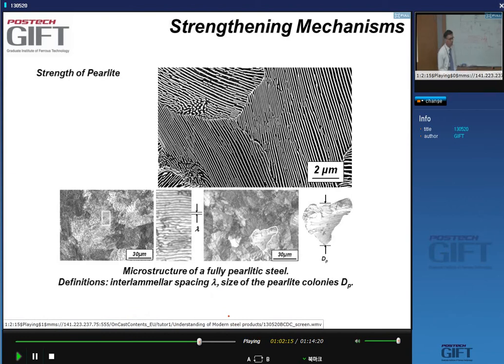Now, most of our steels are not purely ferrite. They're multi-phase. For instance, if you look at pearlitic steel, this is a purely pearlitic steel, we have lamellas of ferrite alternating with cementite lamellas. And we can define islands of parallel lamellas, which we call pearlite colonies. We can give them a size, just the way we give a size to grains, and we can also define another structural parameter, and that's the interlamellar spacing.